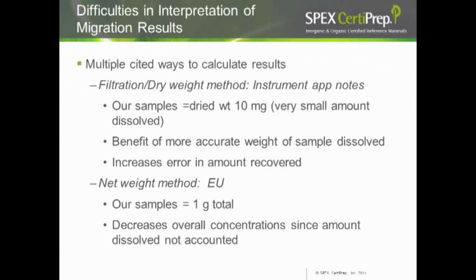One of the problems that we found came down to the calculation of how you interpret these results. Because the samples are extracted or migrating from the toy into the matrix, you can calculate it in 2 ways. Now, there are instrument app notes and different app notes from vendors that suggest that they were following a filtration dry weight method where they took the sample after it had been extracted and they filtered it and then took that filtrate, dried it out, and reweighed it. And that became the basis of their calculation. For us, that was a very, very small amount. The amount that actually extracts into the matrix was about 10 milligrams, a very tiny amount.